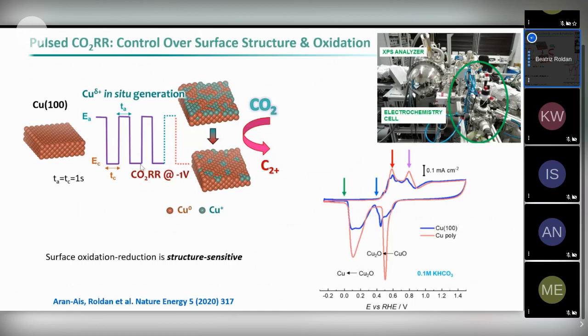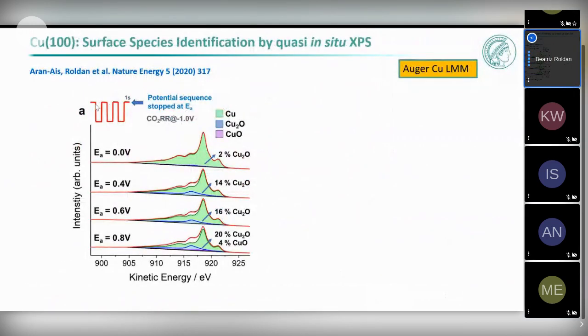So the cathodic pulse is just the normal -1 volt with respect to RHE when we do the CO2 electroreduction. And the anodic pulse is going to be different, and we are going to go to certain anodic pulses in which we know that we are going to be oxidizing our surface. First of all, from the CVs, you can already see that there are some peaks that correspond to the oxidation, but we want to see if we can assign this to copper 2O or copper O. And to do that, we have an electrochemical cell that is attached to our ultra-high vacuum system. So we can do the electrochemical reduction of CO2 here and then transfer in situ and use X-ray photoelectron spectroscopy to monitor the reaction. When you do that, we start first applying these pulses and we stop for 1 second at the anodic potential. You can see it here.